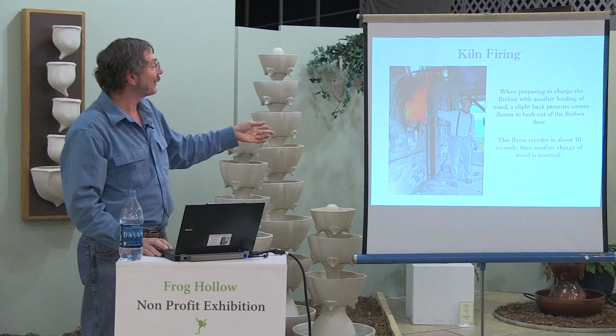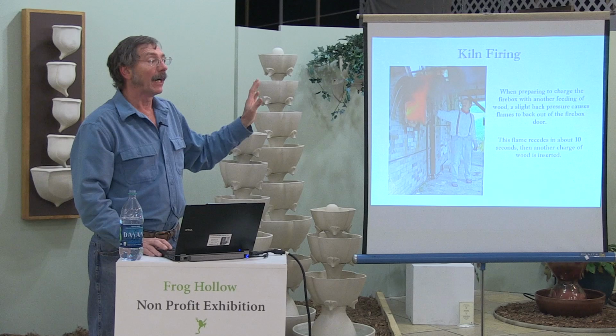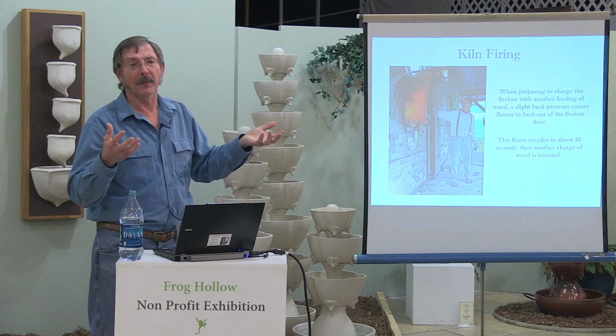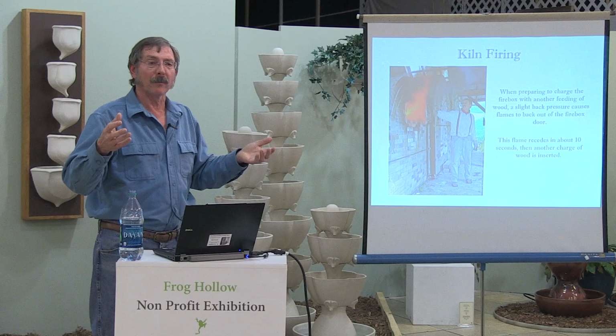But the problem with the really big kilns is they do take a certain amount of time to fire. I fired this in as short as 28 hours, but I didn't get good even heating results. The pots didn't sit long enough. I got everything melted, but uneven as could be. So I've extended it out to about 40 hours, which seems to be optimal for me. But that means you're stoking day and night for 40 hours.